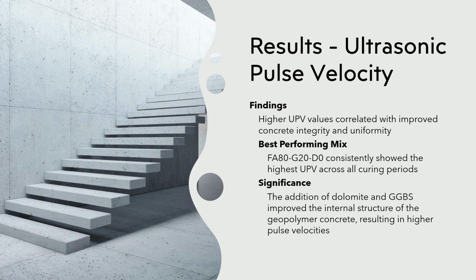Ultrasonic pulse velocity tests showed that adding dolomite and GGBS to geopolymer concrete improved its internal structure. Higher UPV values indicate better quality and integrity of concrete. Mixes with these materials showed faster pulse velocities at 7 days, 28 days, and 90 days compared to the mix without them. The Fa80G20D0 mix had highest UPV values, meaning it was densest and had the least internal defects.